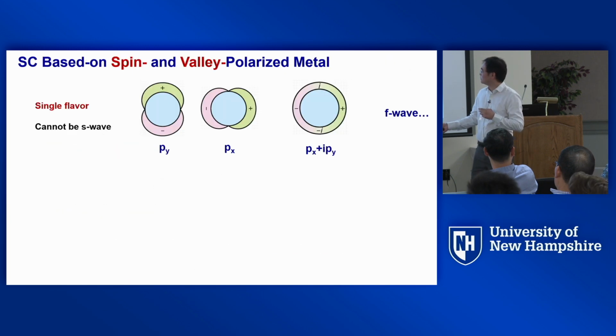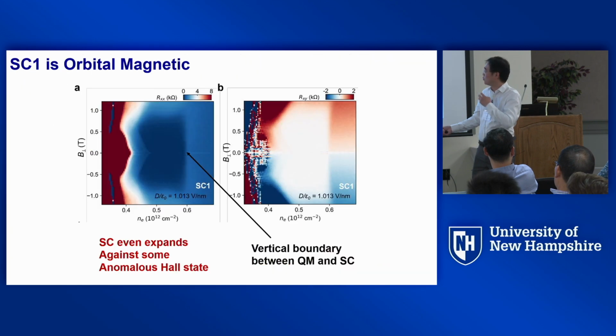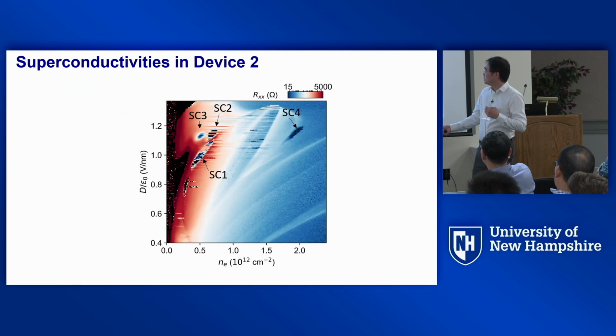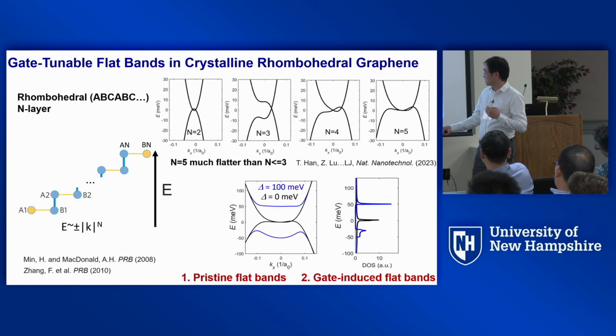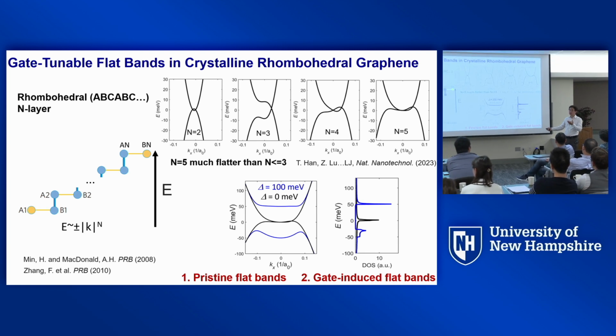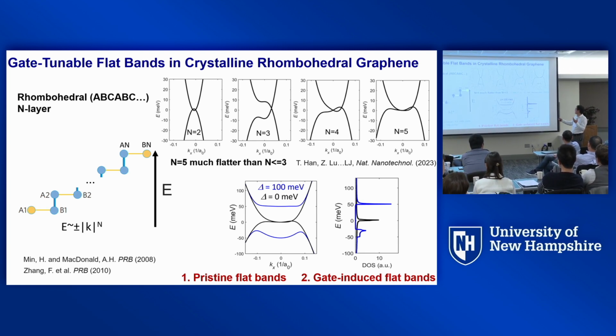And we sort of, at the single-particle level, have some understanding of why that may be the case, because the k to the nth dispersion is not perfect. That's when you neglect a lot of hoppings. But when you do include them, you get this trigonal warping, you get more subtle features. As you can see, the band is already becoming something like a Mexican hat. Although that's more for the valence band than the conduction band, if it's too thick, I suspect that may kill the flatness of the band. So it may not be the thicker the better.